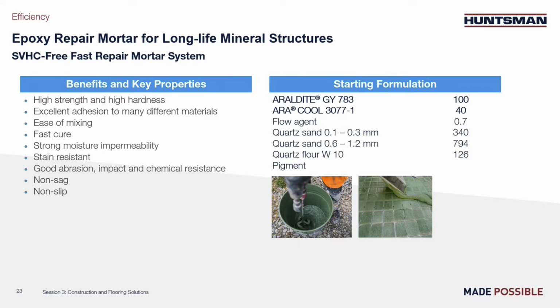This is our example. You can see on the right the simple formulation with different particle size sands, enabling a good packing of the filler. So generally, for mortar, the goal is to deal well with viscosity, and for repair, with fast reaction. Lots of different hardeners can be used for this type of application. Why lots? Because here the appearance is less of an issue than with self-leveling application, as we are going to see on the next slide.